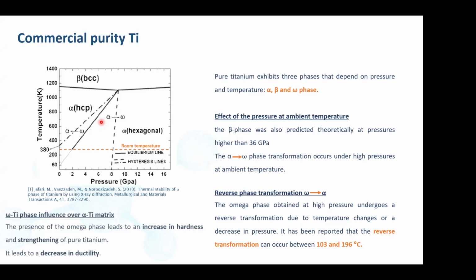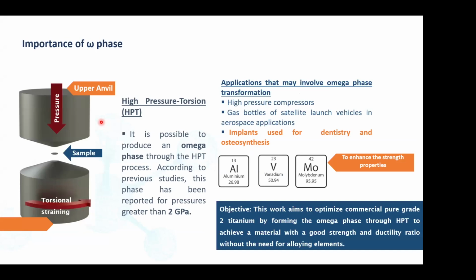So usually the omega phase transformation can happen by pressure. The reverse transformation in very pure titanium can be reversed by removal of the pressure, but also it can be removed by increasing the temperature somewhere between 100 and 200 degrees C. So if we apply high pressure torsion to commercial purity titanium, we can get the omega phase stable in a high fraction. And the omega phase usually has a higher hardness, and it may be used in some interesting applications, especially because we can then increase the strength of commercial purity titanium without the need to add alloying elements.